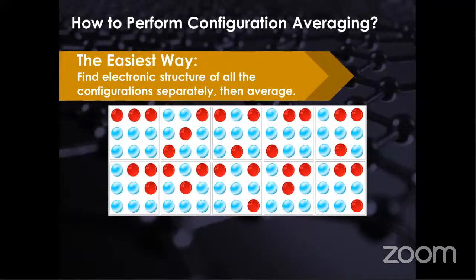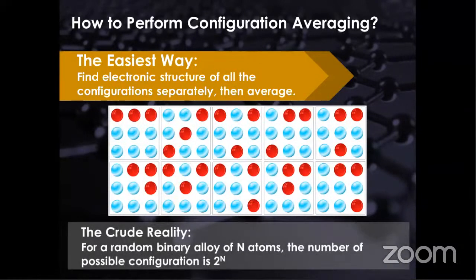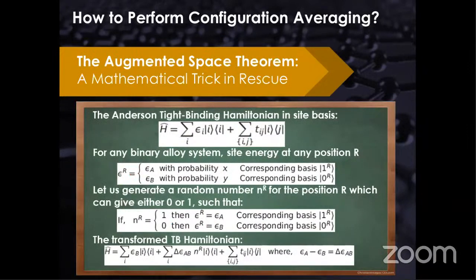Now, how can we do configuration averaging? We can always do averaging by calculating on separate systems and then taking the simple average. But the problem is that for n number of atoms, the number of possible configurations is of the order of 2 to the power n for a binary system, and it cannot be done, because n is very large. There is a mathematical trick which is called the augmented space theorem. This is by Abhijit Mookerjee long ago.